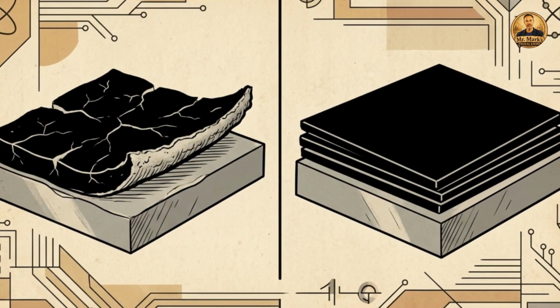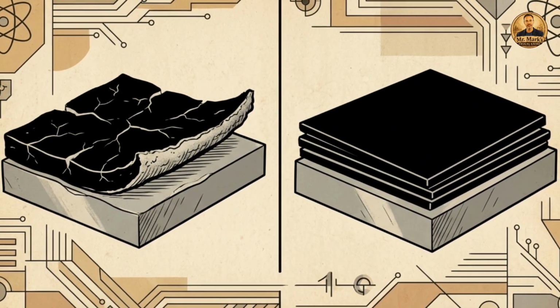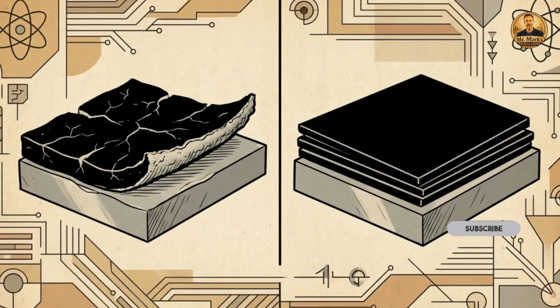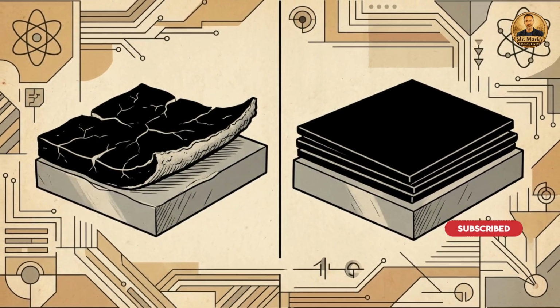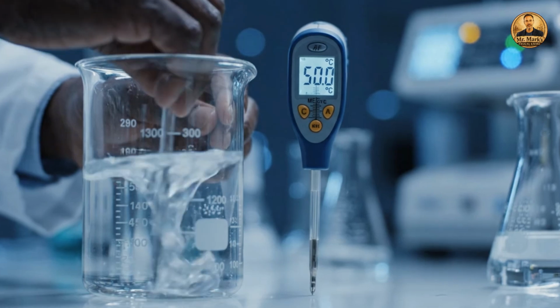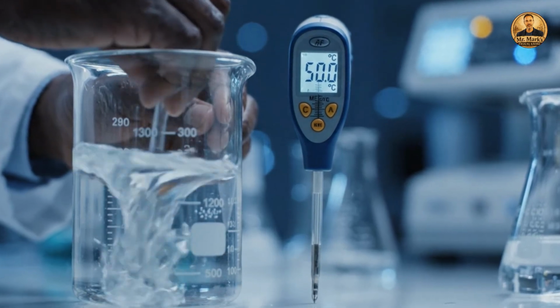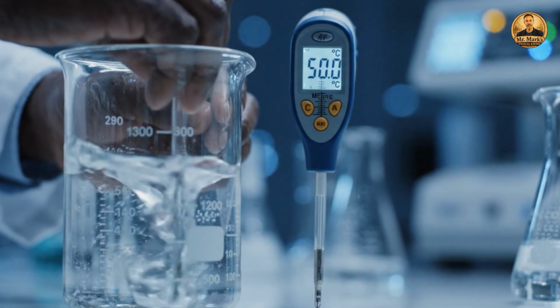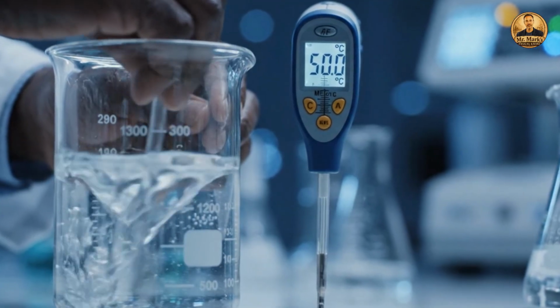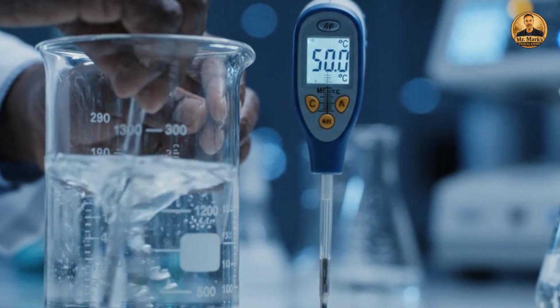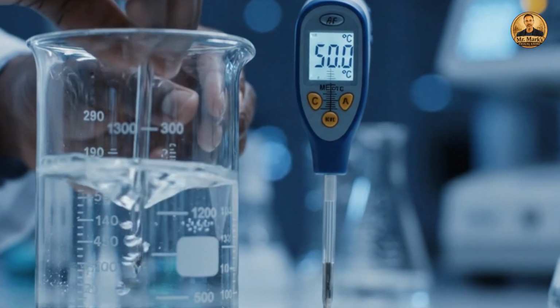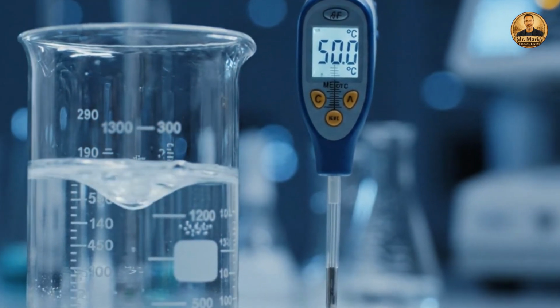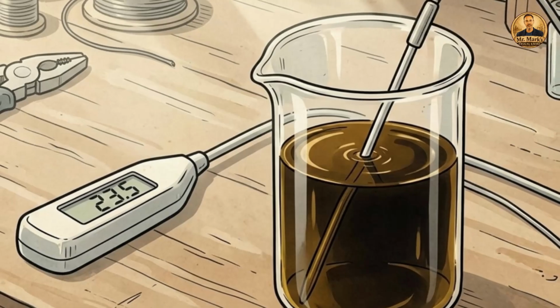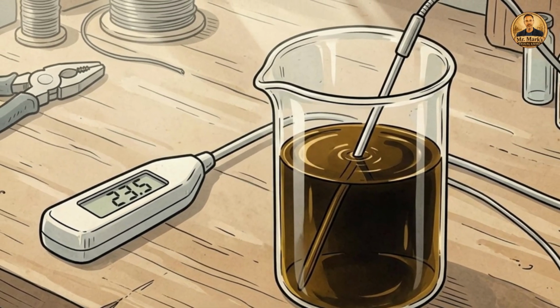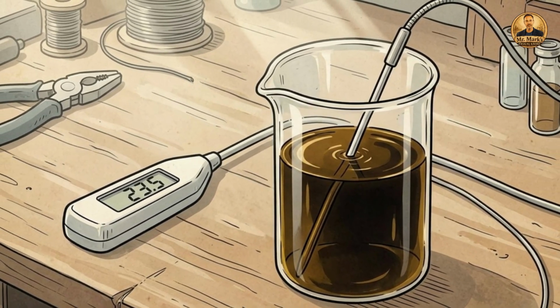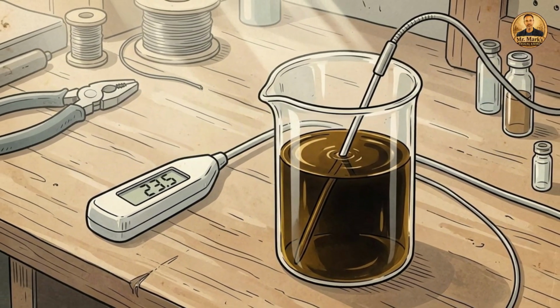Thin coats, fully dried, build a denser and more adherent layer. Here is the technical detail that almost nobody mentions, and it is the difference between a treatment that lasts one season and one that lasts over a decade. The CCI protocol specifies heating the tannic acid solution to 50 degrees Celsius before application. Not boiling, not warm, 50 Celsius, which is about 122 Fahrenheit. A cheap digital thermometer gets you there.